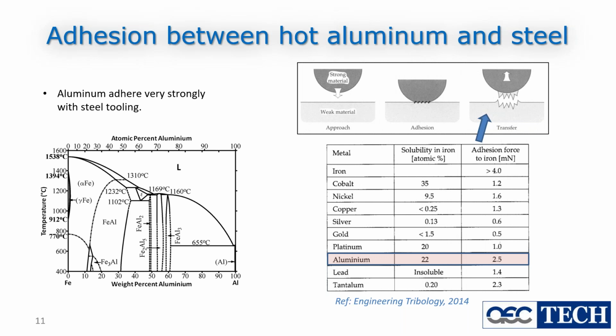So for iron to iron, it's the biggest. It's no surprise because iron to iron, they diffuse into each other and it makes it the same material. After that is iron to aluminum, which is a 2.5. So if you compare the aluminum to copper, for example, the adhesion force between the aluminum and iron is double the adhesion force between iron and copper.